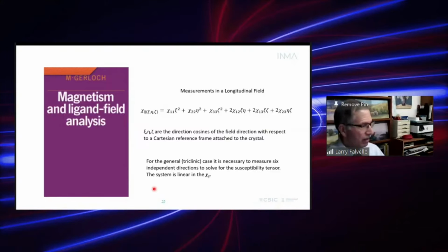Okay, if you have a triclinic crystal, that's a double-edged sword. If you have a triclinic crystal with one molecule in the unit cell, that's the best case scenario for maximizing information because the crystal tensor is the molecular tensor. But for a triclinic crystal, you need to make more measurements. There's not a problem if you can find 6 axes to orient the crystals along and make the measurements.